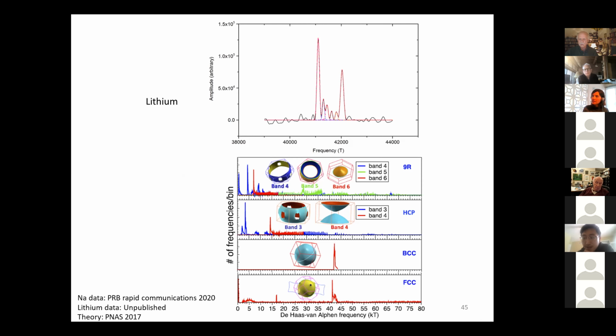Yeah. So basically, there are many things that can have dynamic disorder. It can be phonons, and that is typically temperature driven. I mean, you go to a more disordered phase. And also with pressure, you're changing the phonon spectra, you get soft phonons, so that another structure becomes more favorable. But you can also have zero point effects. So if the zero point motion is enhanced under pressure, and that is also dependent on the structure, you can get these disordered phases. I think the other things are electronic distortions, like Peierls or Jahn-Teller effects, that cause motion to remove the degeneracy. So there are many different reasons for disorder to be created under pressure.